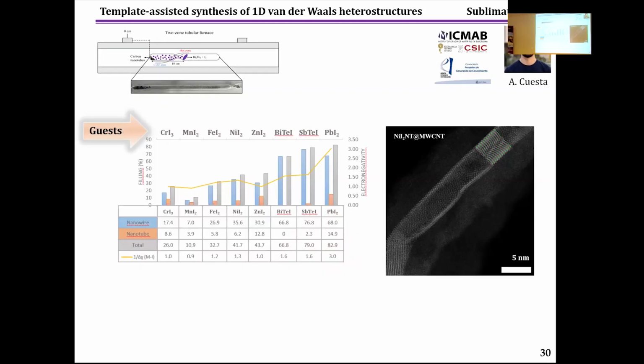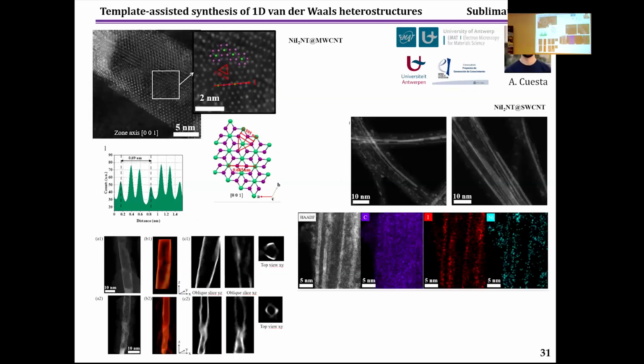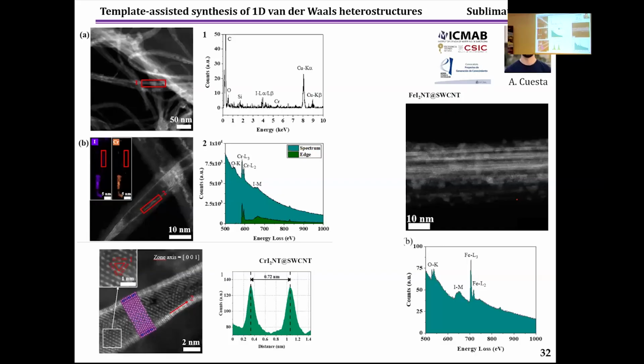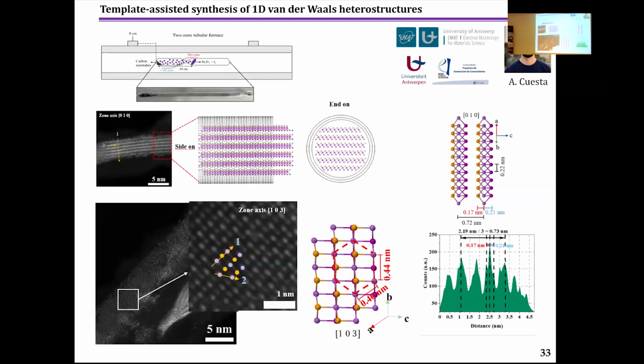So these are preliminary studies which we are planning to perform also along with theoretical and characterization work in order to understand how these materials grow. As I mentioned, he has filled other systems which have been characterized during his stay at EMAT in Belgium, and he has been able to characterize the crystallinity of the system, and these materials have also been encapsulated inside single-wall nanotubes. These are also iron iodides. As I said, the approach is versatile, and we were able to detect the presence of the nanotubes inside.